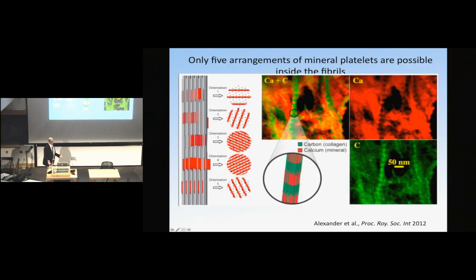So we performed some TEM studies. To make a very long story short, we could see mineral. This is a TEM EELS study, so we're looking at electron energy loss scattering through the materials. We could see banded patterns in calcium, banded patterns in carbon, and we put these together. We could see very clearly what the rest of the TEM community observes, which is a banded structure between mineral and collagen. And then we can also see mineral is clearly on the outside of the fibrils. These are 20 nanometer thick slices. So we suspect that in this portion of bone we have mineral all over the exterior of the fibrils.